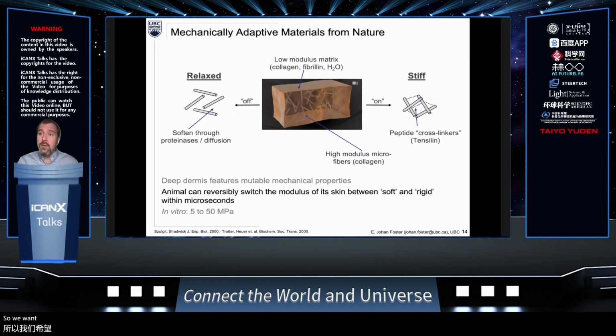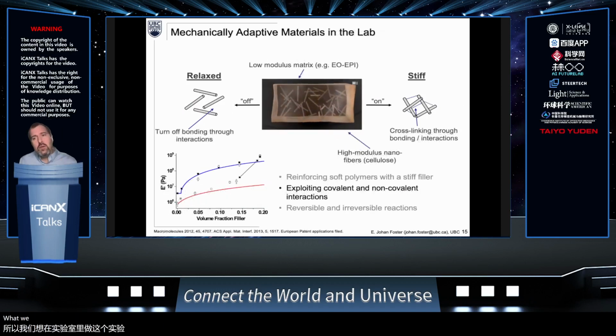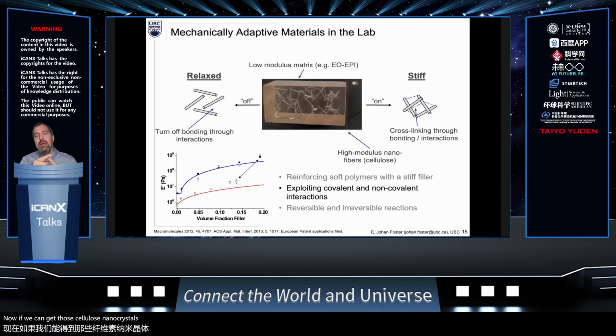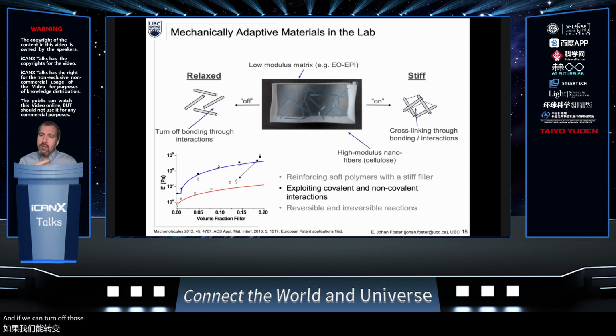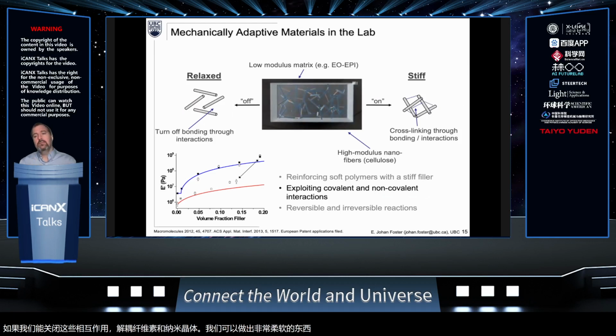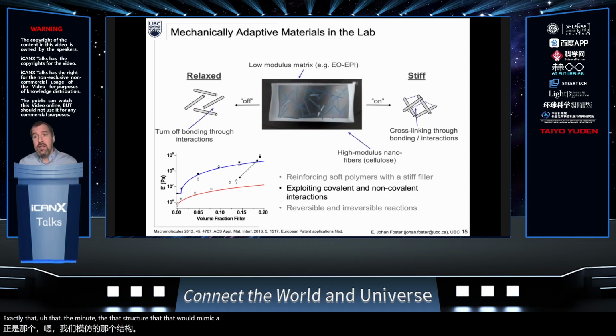So we want to do this in the lab. What we do is we take a soft modulus polymer and we reinforce it with our cellulose nanocrystals. Now, if we can get those cellulose nanocrystals to interact, we can make a stiff material. And if we can turn off those interactions, decouple those cellulose nanocrystals, we can make something that's very soft. So exactly that structure that we mimic of the sea cucumber. So in the bottom left, we have a logarithmic scale of stiffness versus volume fraction of the cellulose nanocrystals we put into that polymer.